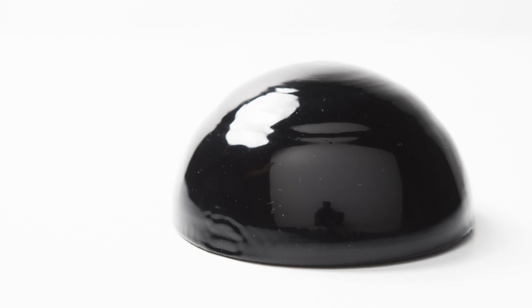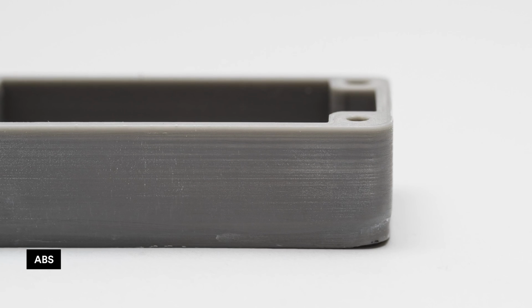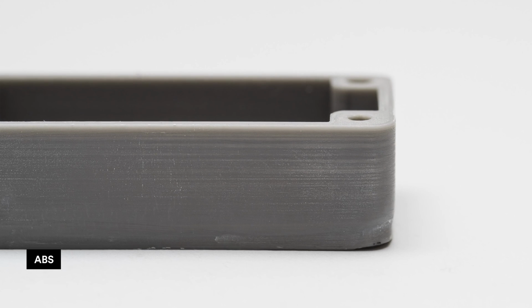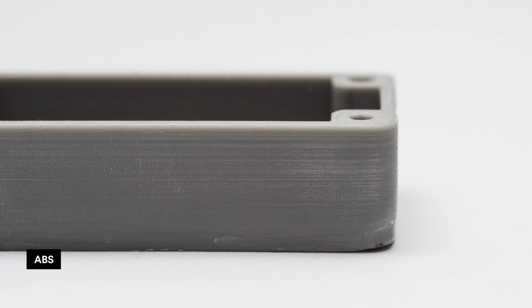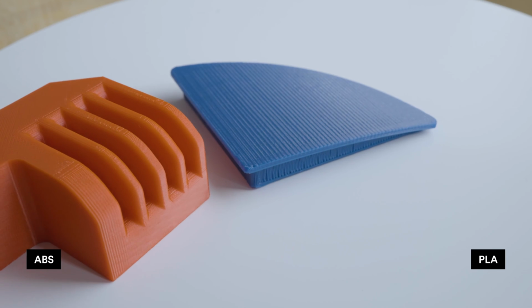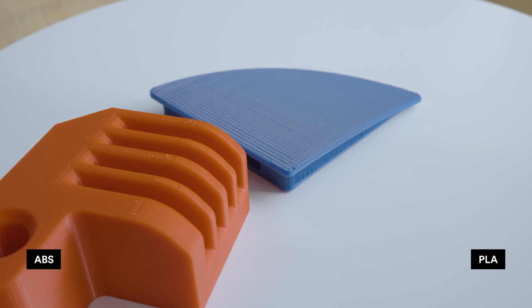Surface finish and post-processing. The nature of printing with FDM materials means that for both ABS and PLA, the print layers will be visible after printing. Acetone is often used in post-processing to smooth ABS parts and to remove layer lines. This results in a glossy, smooth finish. ABS can be easily sanded and is often machined, for example drilled, after printing. PLA can be sanded and machined, however, greater care is required. Acrylic paint can be added to both PLA and ABS.